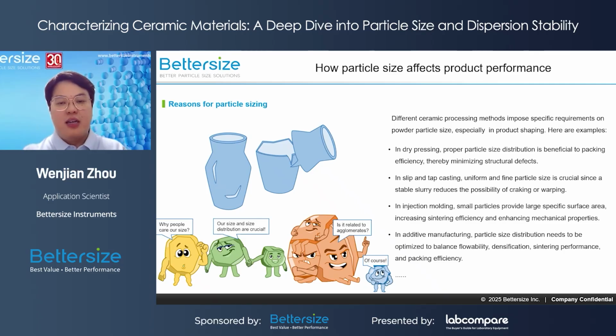In dry pressing, ceramic powder will be filled into a die and pressed by punches, whose particle size and distribution needs to be specified to make sure good packing efficiency. Sometimes particle sizing for granule is also necessary, since granule with appropriate size increases particle flowability. In slip and tape casting, ceramic slurry will be poured into a mold. Control of particle size is critical since the slurry stability is greatly affected by particle size, and a stable slurry reduces the possibility of cracking or warping.